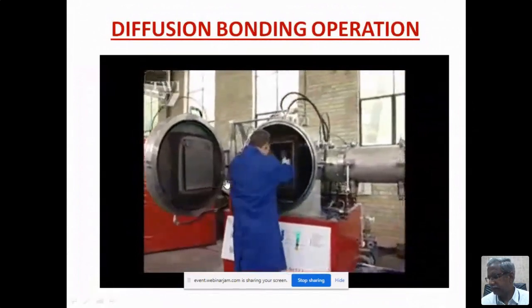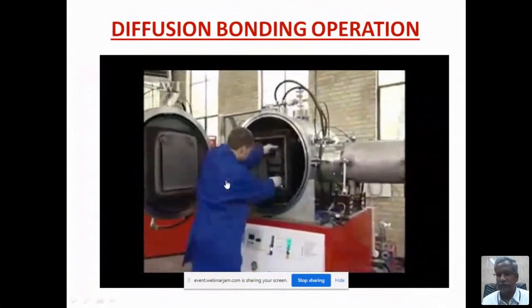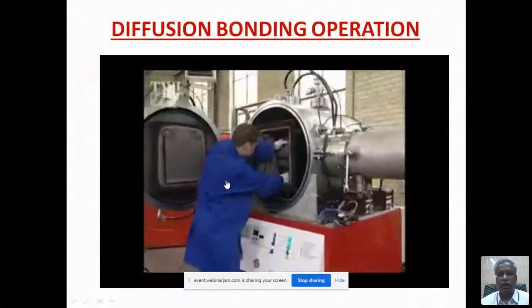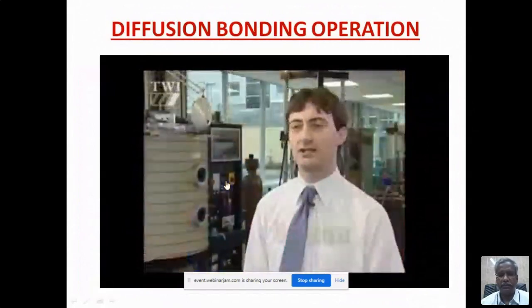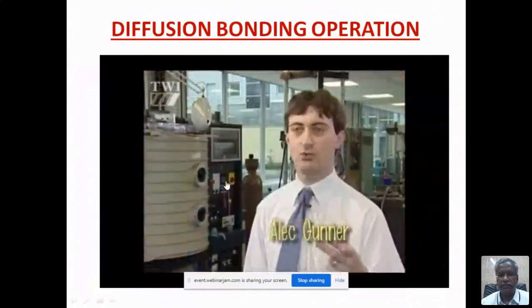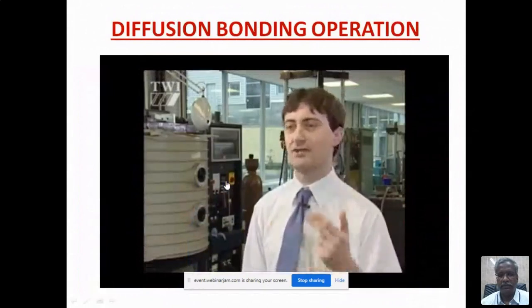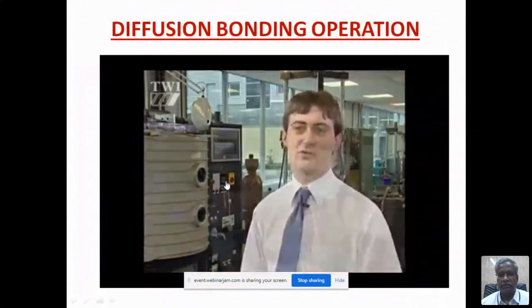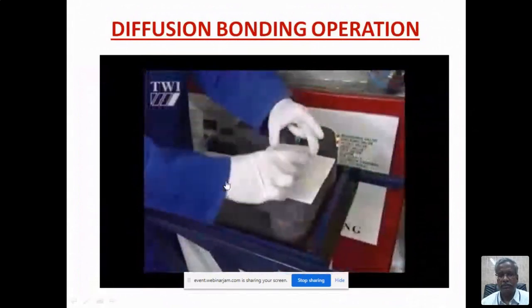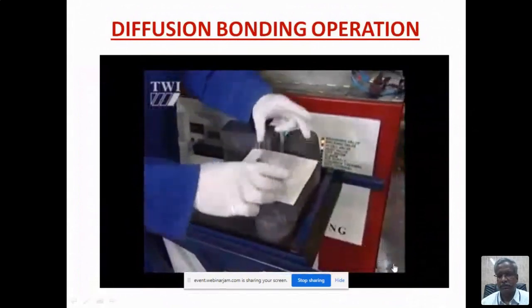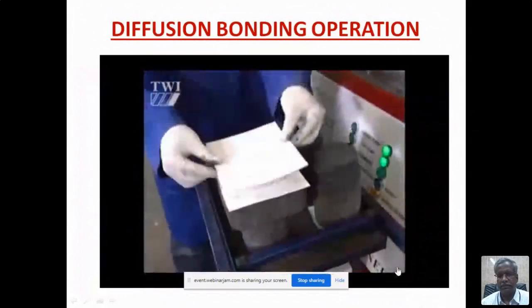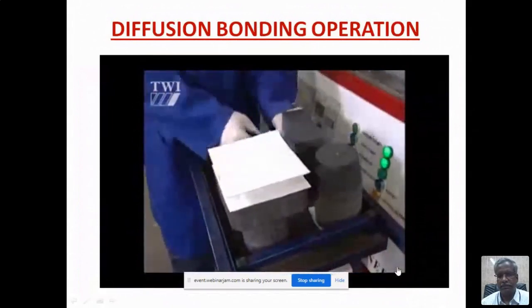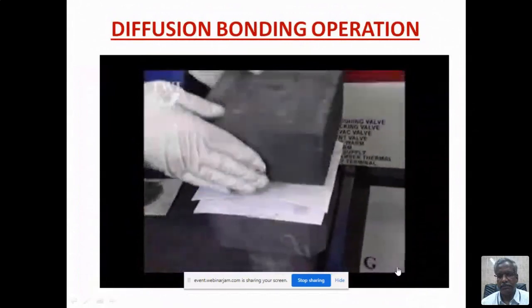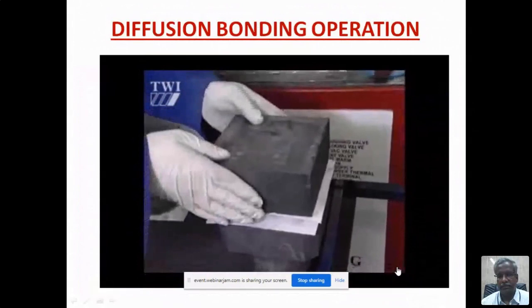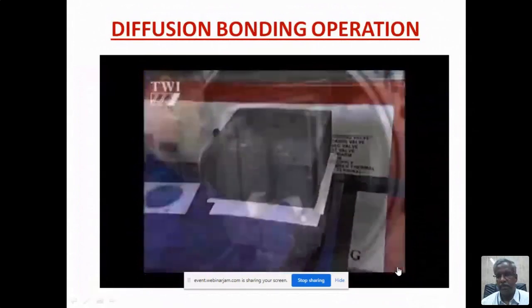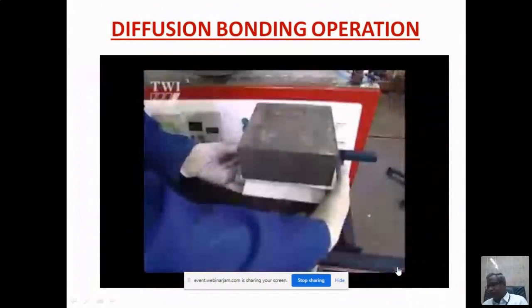It's a very simple process. The equipment is really not a lot more than a hot box with a press running through it. It works on the principle that if you heat components up to the point where the atoms on the surface have enough energy to start jumping across the gap, then they will bond together. So you would take two components with a very good surface, push them together, heat them up and wait. You form a bond which is metallurgically perfect. If you took a section through that bond and polished it, then if you've got the conditions right, you won't be able to see where the bond line is.